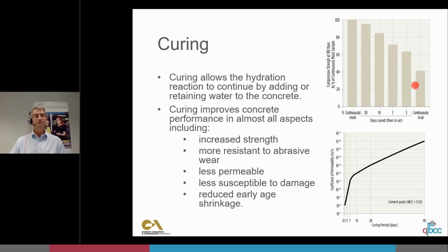So this top diagram shows, in a similar way to what that compaction diagram did, the relative strength on the vertical axis. So again, if we've ordered 25 MPa concrete, 100% would be achieving that 25 MPa strength. And it's got different curing regimes on the horizontal axis, going from the best possible, where it's continuously cured in a moist environment, to the worst, where it's just been left to cure in the air. And you can see that when it's left to be cured in the air, so in this situation, we've placed the concrete, we've finished it, and we just walk away, we're only achieving 40% of the strength that we should be achieving.